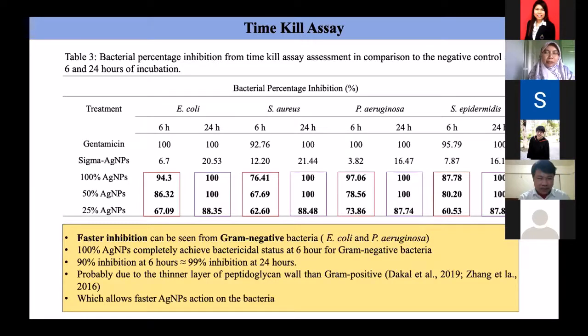using the silver nanoparticle, it was at 6 hours. This means almost 90% inhibition can be observed after 6 hours and up to 100% after 24 hours. And we also found that the gram-negative shown the most sensitive effects towards the silver nanoparticle.